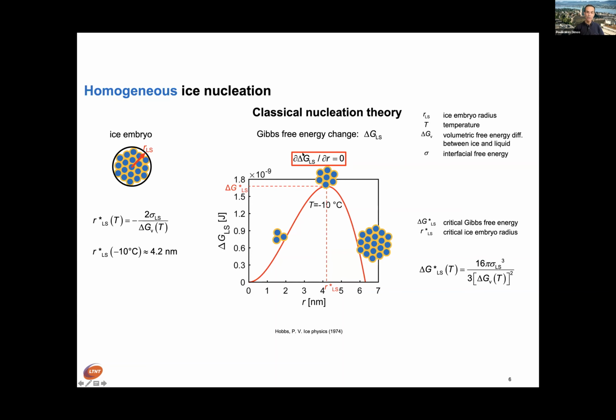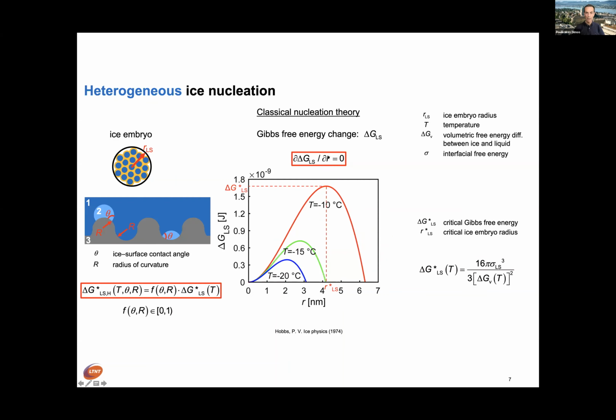Of course, this barrier is a function of temperature, and the lower the temperature, the smaller the barrier. So you can reach the point at about -40 where there is no barrier, and every embryo will grow. But generally speaking, even at a temperature of -10, -15 degrees, you really have to wait for icing to take place on a surface, and at 0 degrees, this barrier is much higher. So effectively, you're going to have to wait a very, very long time for icing to take place at 0, and that doesn't really happen in reality because our temperature keeps changing. If temperature is falling in applications or in nature, 0 never has a chance. We never stay at 0 for a very long time for ice formation to take place. It always occurs at a metastable state when the liquid is at a temperature below 0.